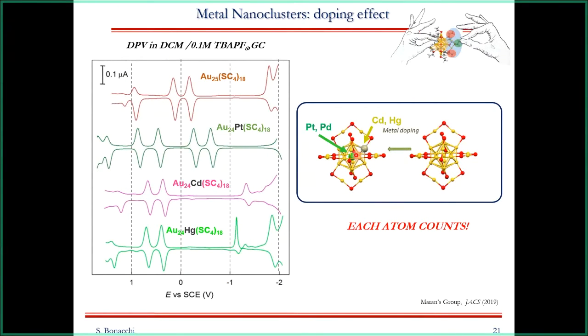And another intriguing aspect, to me at least, is the possibility to really change the one metal atom in the kernel. So not anymore the size, the same kind of size, the same kind of core structure, but with different metal doping, with different metal ions, you can clearly change the electrochemical properties of this cluster. So you can play with the metal doping effect to modify the kernel but not the structure, and to induce a dramatic change in their electrochemical properties. So again, in a philosophy in which each atom counts in the physicochemical properties of this cluster.